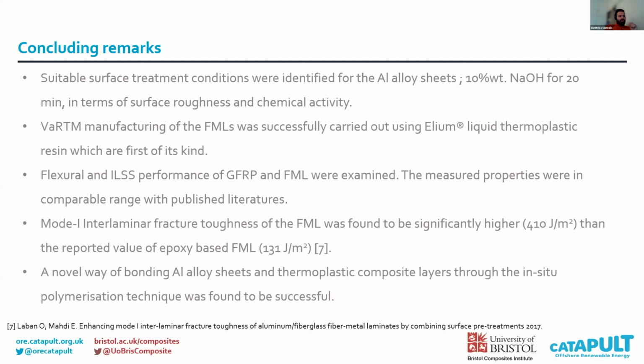Mode 1 interlaminar fracture toughness of the FML was found to be significantly higher, with a characteristic number of 410 joules per square meter, compared to the reported value of 131 joules per square meter for epoxy-based FML in the literature, and also with the same configuration, of course. Also, a novel way of bonding aluminum alloy sheets and thermoplastic composite laminates through the in situ polymerization technique was found to be successful.